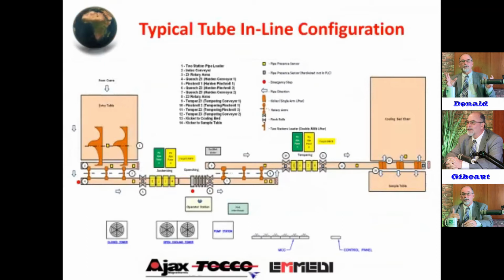So here is another type of line. It's an inline system. Same components, except it's a lot longer. That's where the U shape comes in. It's wider, but it's not as long as the inline. But again, you have an entry table, fed in front of the austenitize, the quench. Item 8 is a transfer table over, and then you go through the temper, sample position again. Right here now off the cooling bed. These people have a position here for quench samples, but they wanted a sample table here at the cooling bed. And then it goes across the drag chain cooling table.